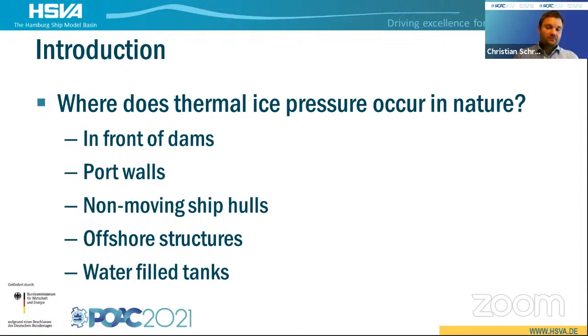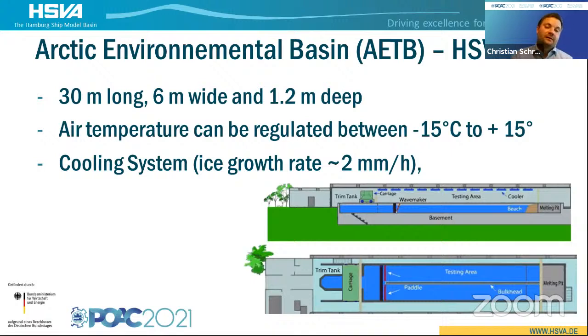Where does thermal ice pressure normally occur in nature? Mostly these effects occur in front of dams, port walls, non-moving ship hulls, and offshore structures, but also in water-filled tanks in case they freeze, the area is of course restricted in the tanks, and they are heated up again. The tests were done in the Arctic Environmental Test Basin of the Hamburg Ship Model Basin. The overall facility has a water tank area of 30 meters long, 6 meters wide, and 1.2 meters deep. We can regulate the air temperature down to -15 degrees to prepare the ice, but also heat the room up again to up to plus 15 degrees. The cooling system can achieve an ice growth rate of about 2 millimeters an hour as a maximum.